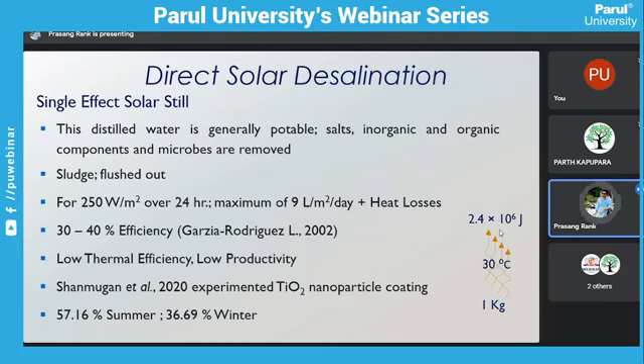Also Shanmugam et al. in 2020 experimented that if we keep a nanoparticle coating at the bottom of the still, the evaporation will increase. They studied titanium dioxide nanoparticle coating, and they found around 57.16 percent efficiency in summer and 36.69 percent efficiency in winter. So they got an increase of efficiency through the nanoparticle coating, but that is also an expensive thing.